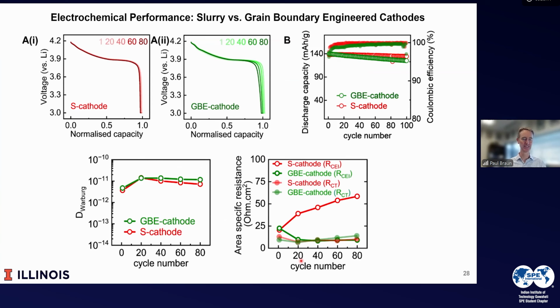If we look in the detail of the electrochemical performance, we can see that the Warburg resistance is very similar, but the big change is in the area specific resistance. And so the grain boundary engineered material has a very low interfacial resistance, while the slurry cast one, the CEI resistance continues to grow. And it continues to grow because as it cracks, it generates new surface. The new surface generates CEI, and that CEI probably then leads to additional cracking. And so from a stability standpoint, minimizing that cracking leads to longer stability or better stability.